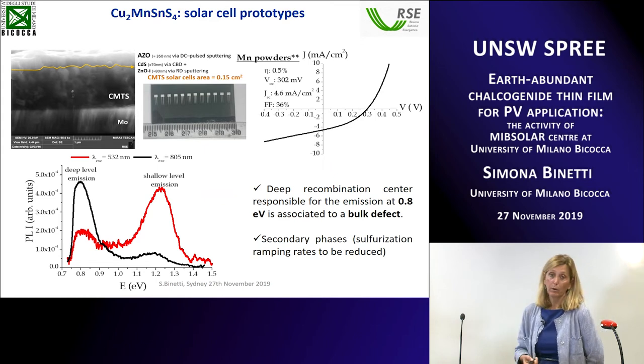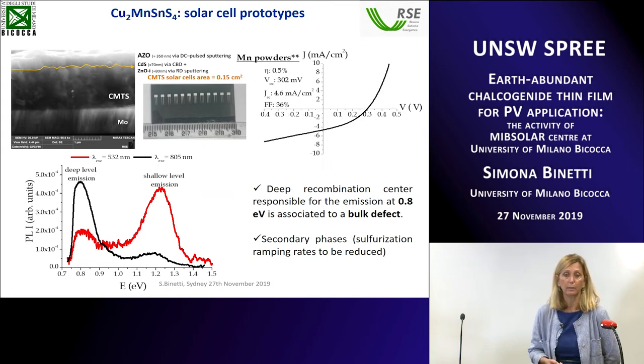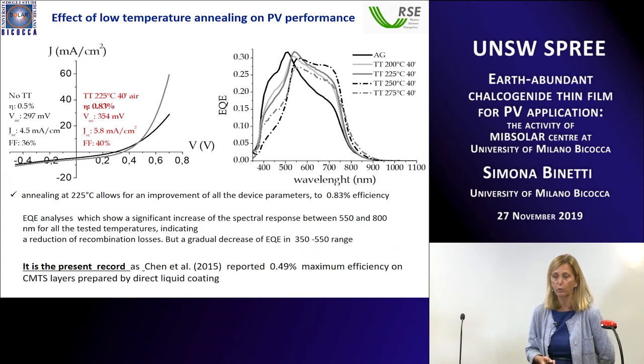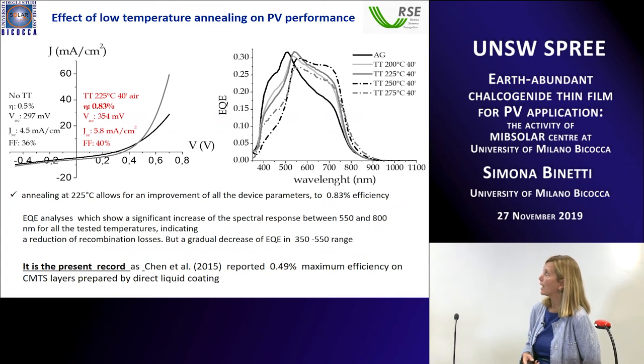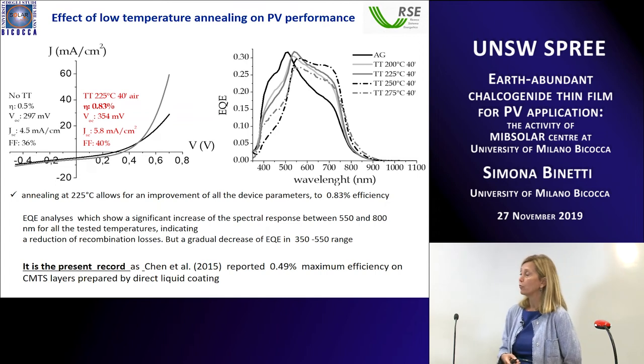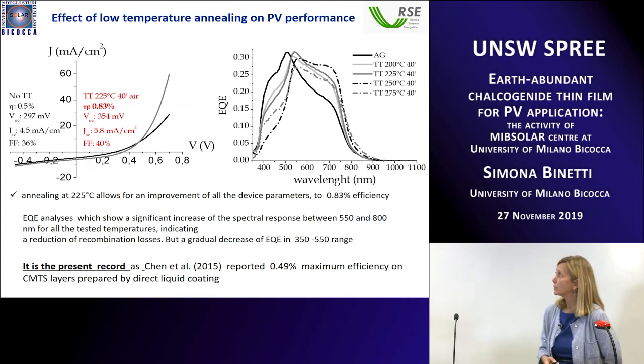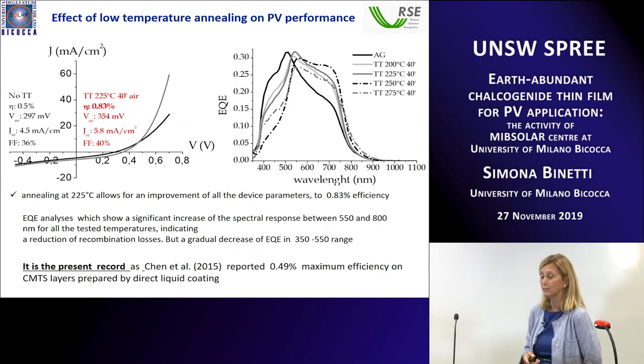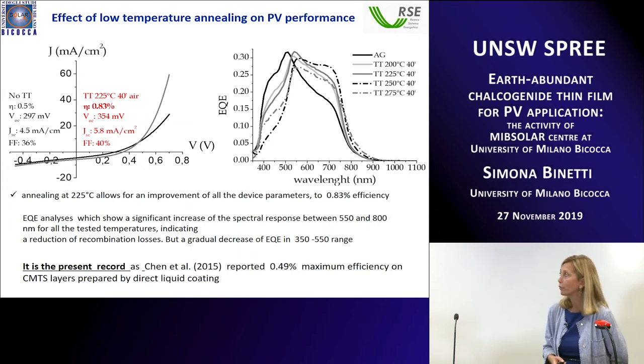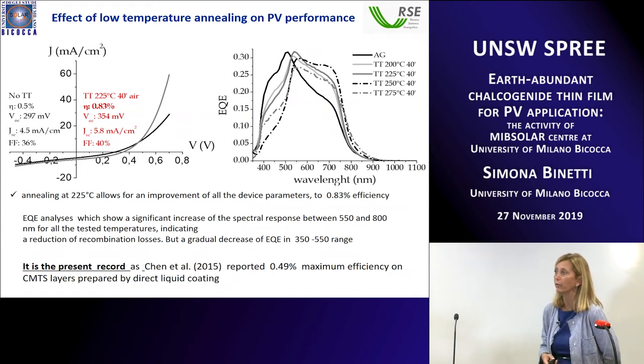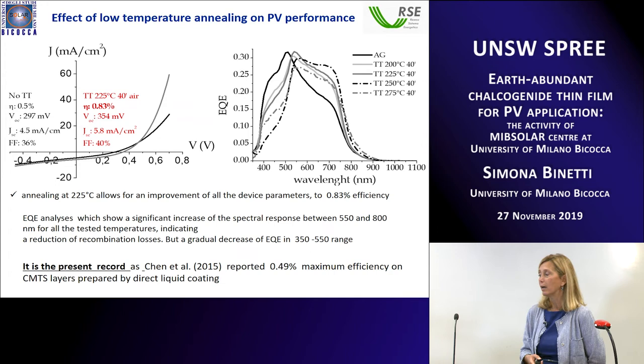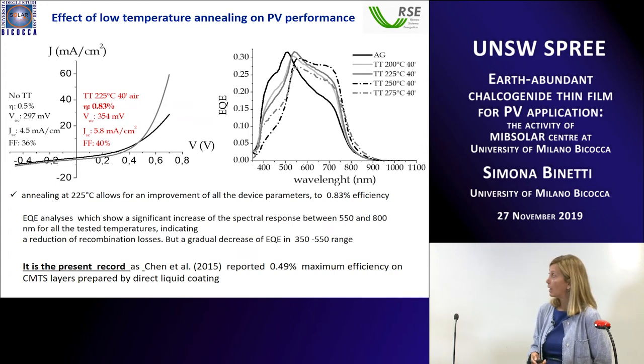We tried to increase our efficiencies with the standard annealing step that is normally performed also in Kesterite. Of course, we have to optimize the temperature, so we checked several temperatures, and annealing at 225 degrees C, we have an improvement of all device parameters, and we have an efficiency of 0.83%. It's very low, I know, but it's the record efficiency at the moment, because the other group that is working on this material got an efficiency around 0.1.